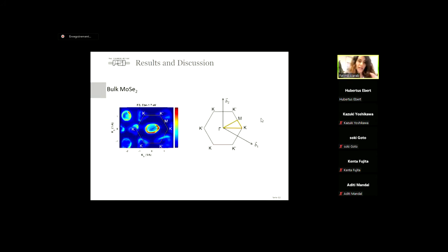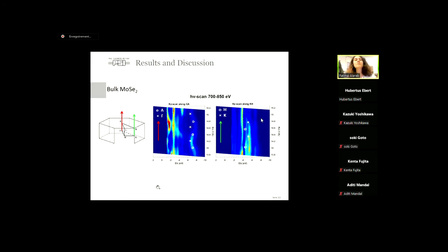So of course we take the material and we start aligning it. We start first aligning it along the gamma K direction. So this is the experiment, and it fits very well with the 2D Brillouin zone. And then, because we want to hit the symmetry points K and H, which are presented here, which are in the KZ direction, it's equivalent to a photon energy dependency or scan. So then we have to find which photon energy corresponds exactly to the K point and H point.